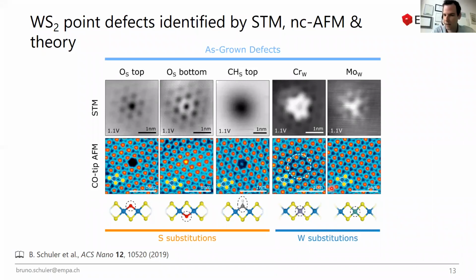So that means it could oxidize, but however, we also looked at samples which have different ages. So like say from the time scale of hours. So Christoph was actually working with me at the Berkeley lab. So we also looked at samples which were immediately transferred in our UHV, and there was not a big difference in terms of oxygen concentration. So we don't think that will happen over time in most of the materials. So there is a few materials which are more air sensitive, of course. Okay. For tungsten disulfide, not so much.